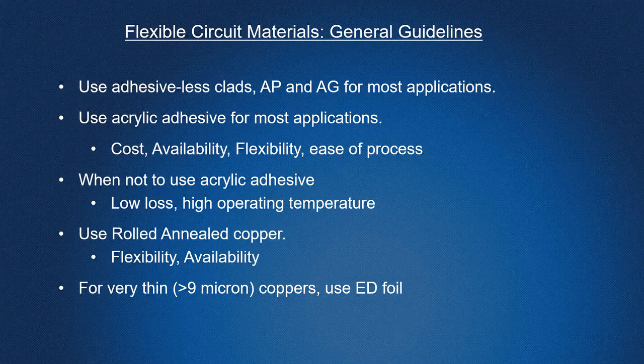One of the things we find with the acrylics, especially in the rigid flex, is we remove acrylic, even though it's in the product, from anything that has a thermal area. So anything you're going to be assembling, we try to use a combination of materials. Even if it's a pure flex job where we're using an LF bond ply, if you're going to be doing lots of assembly and you're probably going to put a stiffener behind it, we're not necessarily going to be using rigid cores, but in that selective area, we'll put prepreg and we'll cut back the adhesive. That way you still get flexibility everywhere you need it.